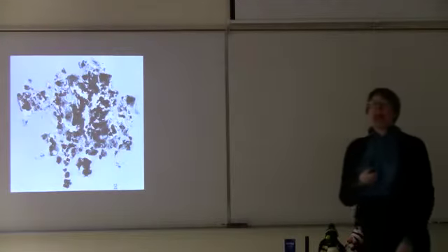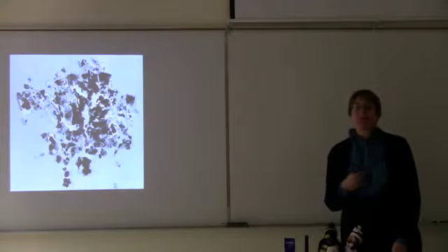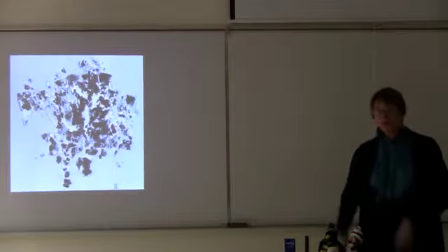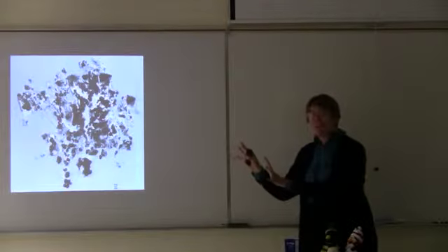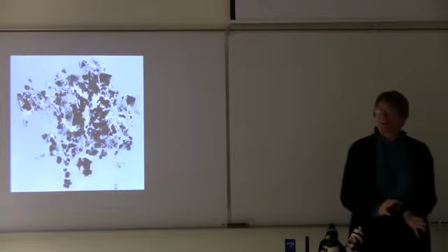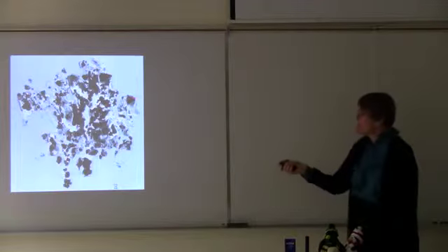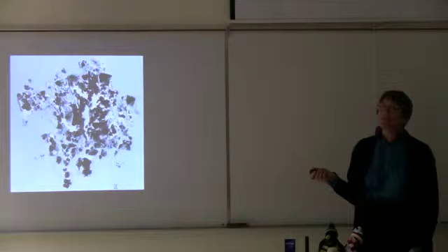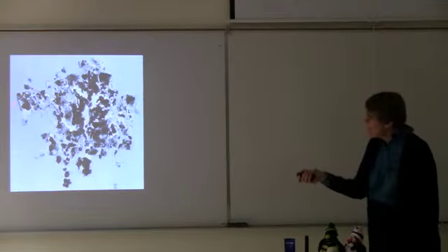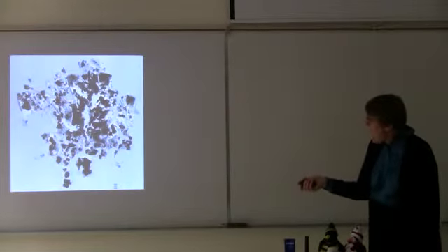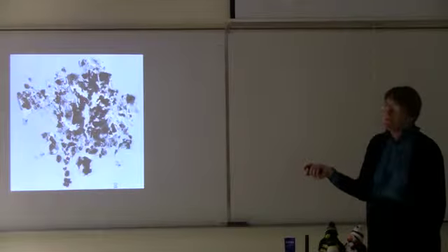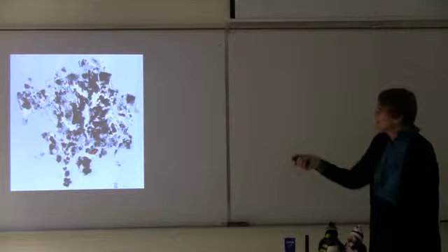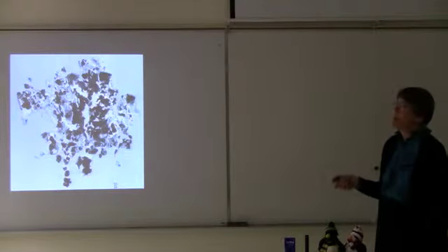Okay, in the same lab, one of Dave McKay's tech people was Kathy Thomas-Caperta, and you all know her from the Life on Mars stuff. While she was doing that in one half of her lab, I was working with her at exactly the same time, and we were interested in looking at porosity in cosmic dust. So these are transmission electron images, and part of the problem we had with this was how do you define the edge of this sample, and therefore to measure porosity in the interior, you have to know where the edge was. So that was kind of the problem we ran into in the end.